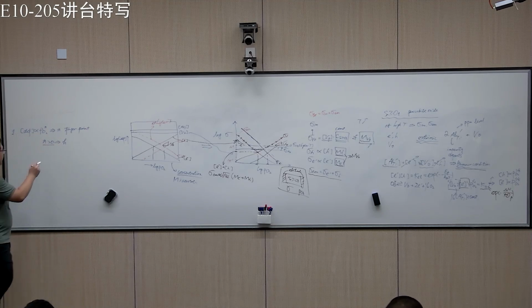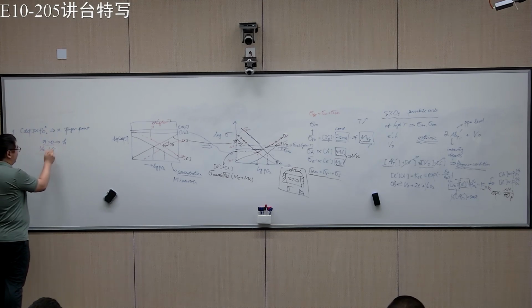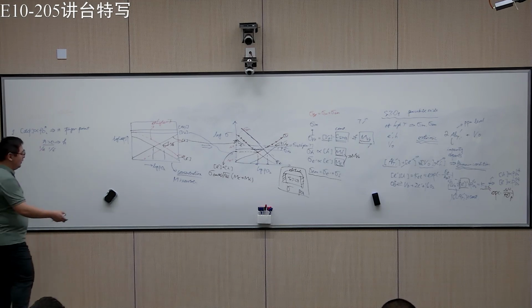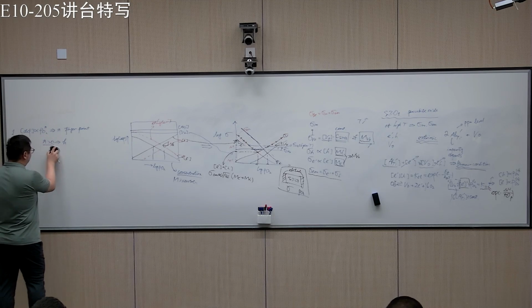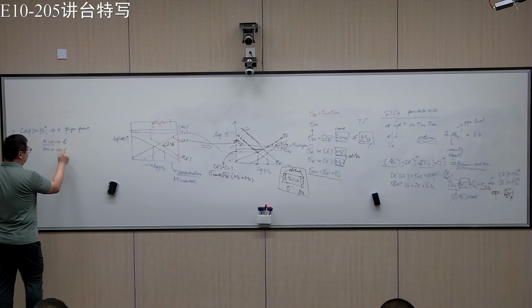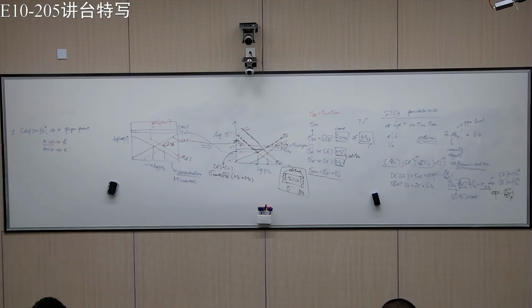Of course, that can be 1/4, 1/6, depending on the specific p-type chemical reaction. And if you have other geometry, not just 1 to 2, things will be more complicated. If n is negative, that should be the electrons.